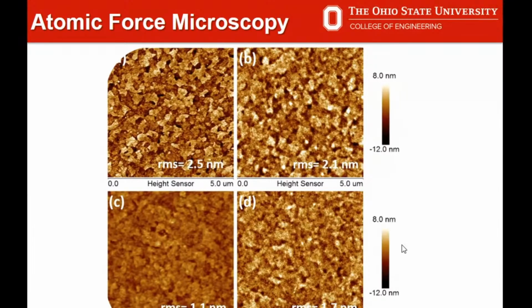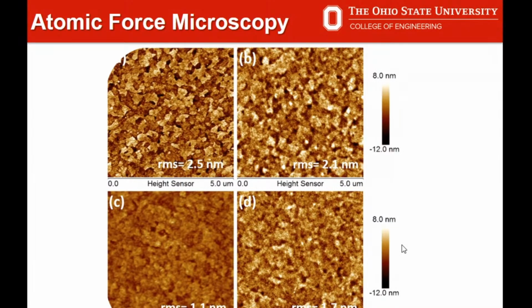So you have to be careful while controlling the instrument so that you could get lower roughness. Again, it depends on the parameters you are using for your material growth. That is the most major parameter, I would say. You have to be very careful while growing your materials. Then you can measure the quality of the sample, and one of the major tools is AFM.